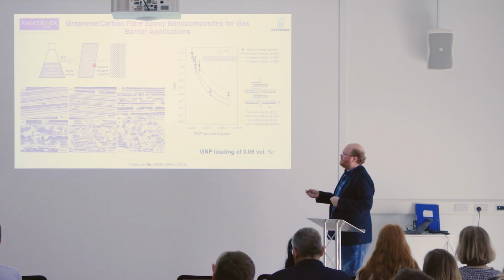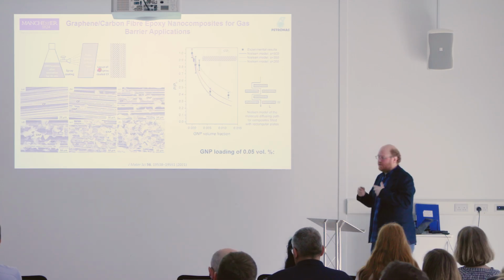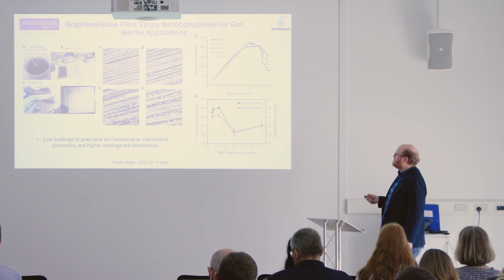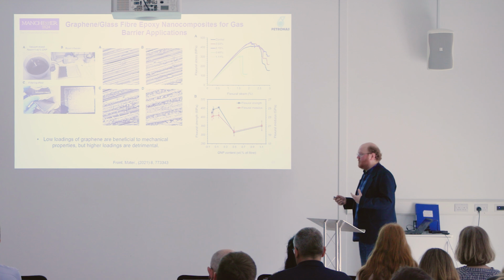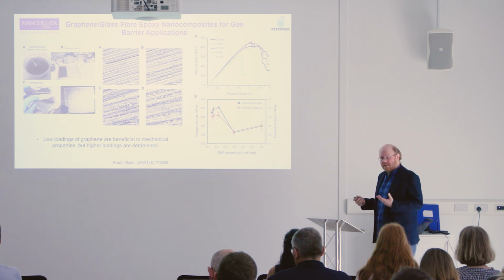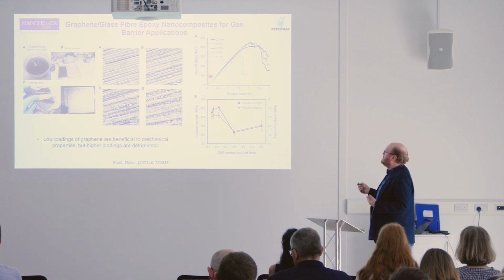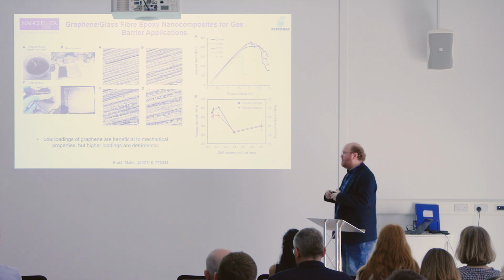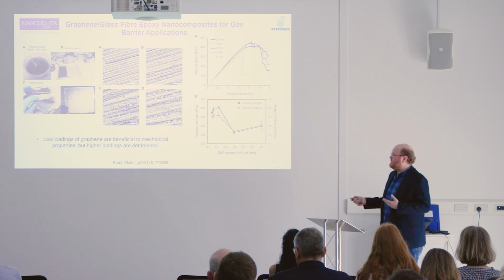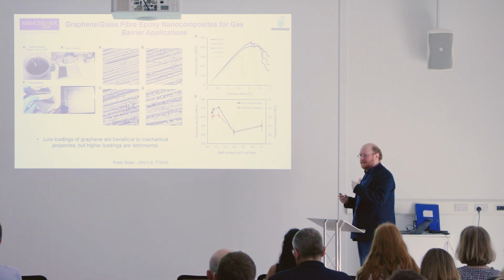So again, that's why we were using this spray coating method, where we're not relying on it, this filtering effect being a problem. And again, when we're looking at the mechanical properties of these composites, we find that very low loadings give us the most benefit. So we see improvements in the modulus and also the strength at low loadings, between about 0.2, 0.3%. And again, if you add too much material, as you can see visually from the SEM here, what you're doing is introducing additional defects.